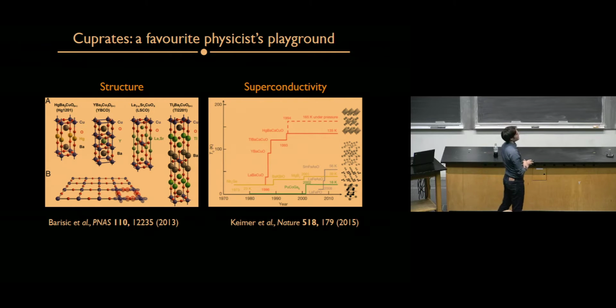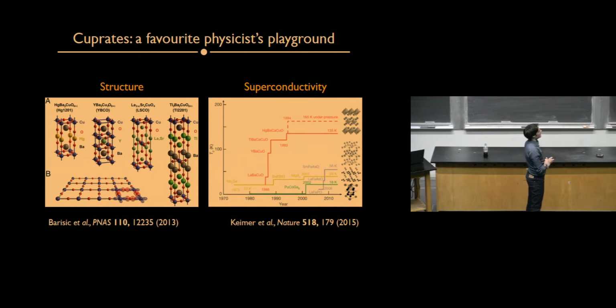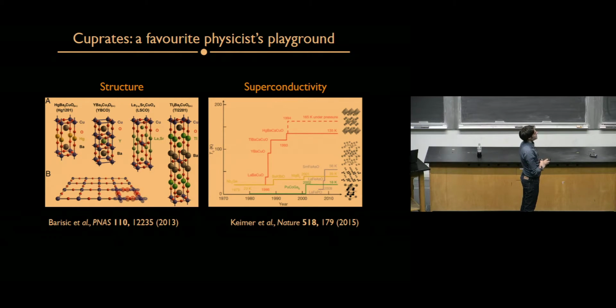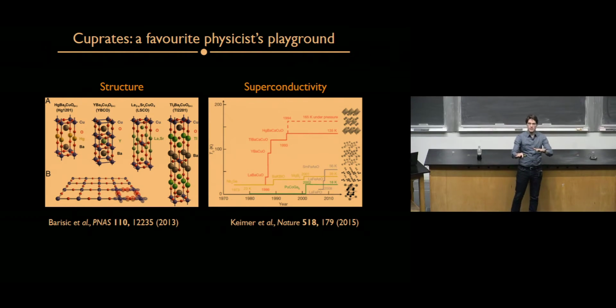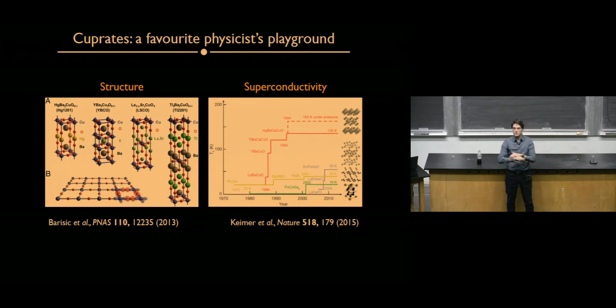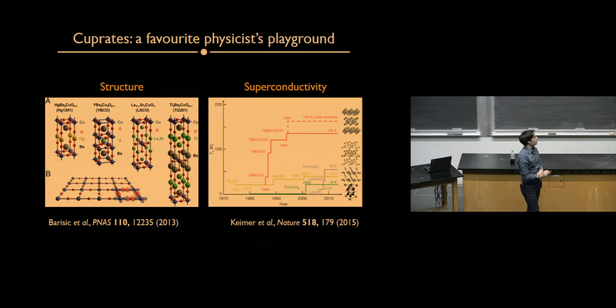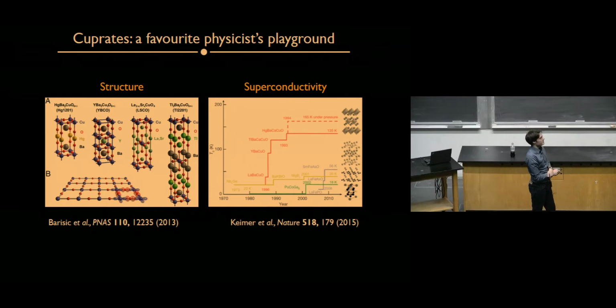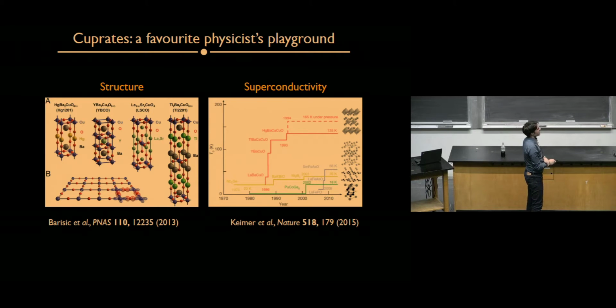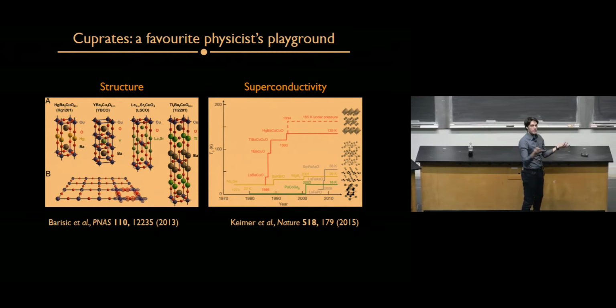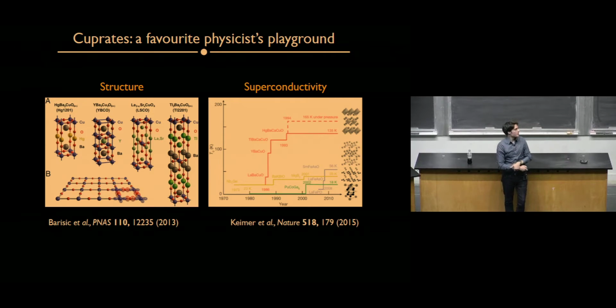So you can have different compounds, but the take-home message of this slide is that the fundamental ingredient in all these structures is the presence of these copper-oxygen planes, which are the crystallographic places in this complicated unit cell where all the interesting phenomena happen, in particular superconductivity. And this is because all of the low-energy electronic states live in these planes. Okay, so the electronic states are the copper 3d orbitals and the oxygen 2p orbitals that are hybridized with each other, and they form the low energy bands out of which superconductivity emerges.